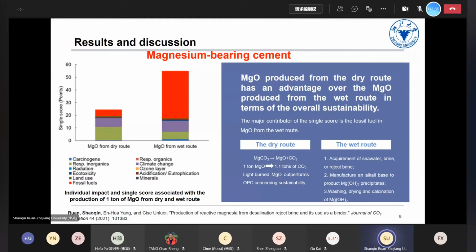The second is the wet route. The wet route obtains MgO from seawater, brine, or rejected brine. You need some alkaline bases to produce magnesium hydroxide first, then you calcinate these products to produce the MgO. But from our experiments, we find that MgO produced from the dry route has an advantage over MgO produced from the wet route in terms of overall sustainability. You can see from this figure, the left one, MgO from the dry route has a lower single score compared with MgO from the wet route.